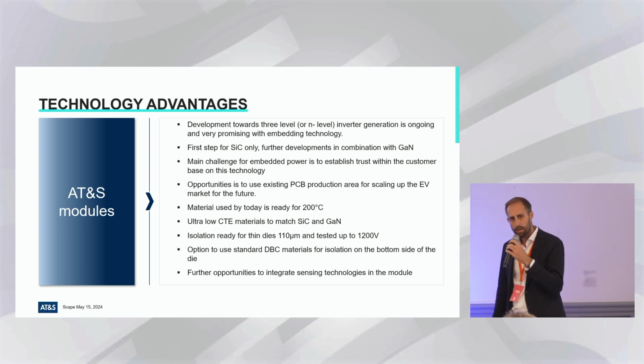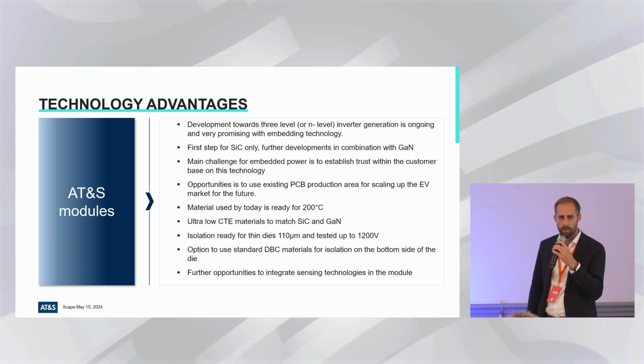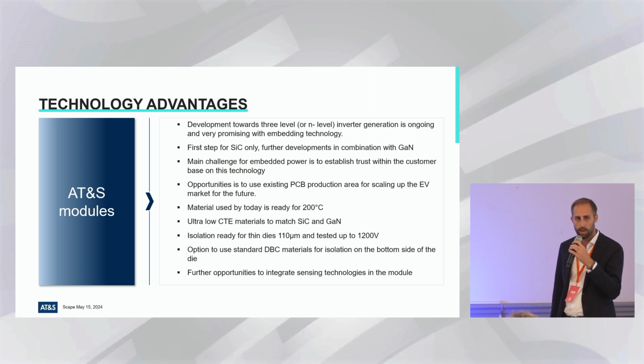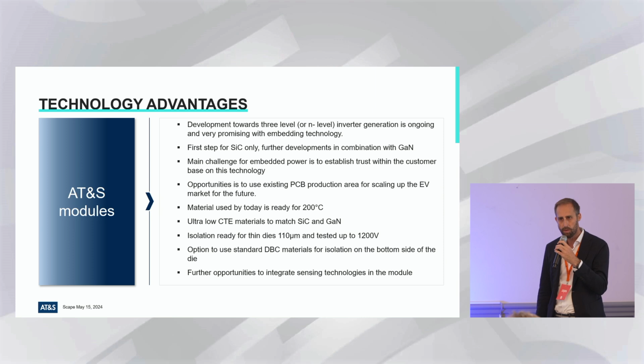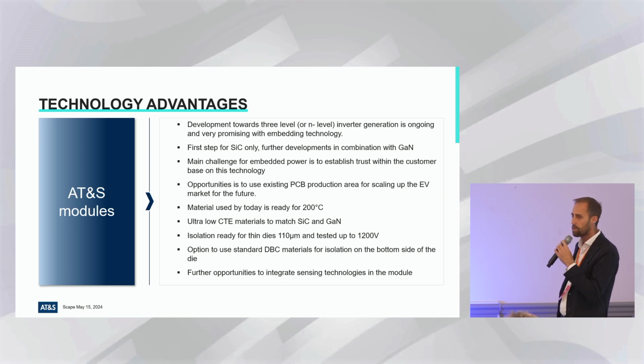From the material side, we can use up to 200 degrees Celsius. That's not an issue for us. We use materials with a very low CTE, which are in line with the SiC and GaN materials. We have isolation ready for very thin dies, between the top and the bottom side of the die. We can also have DBC as a standard solution on the bottom side for the isolation to get the heat out of the system. And we also see further opportunities for sensing already integrated in the module. That's all in a nutshell. Thank you.